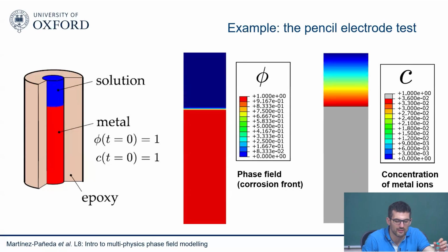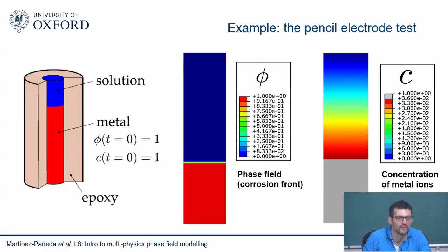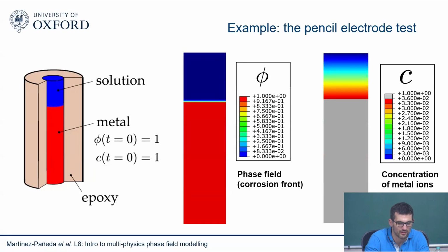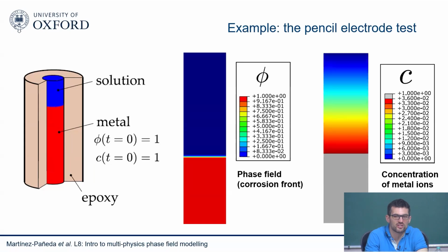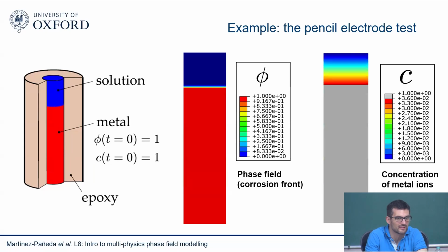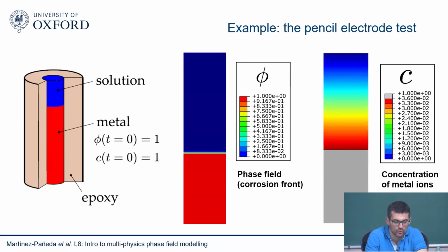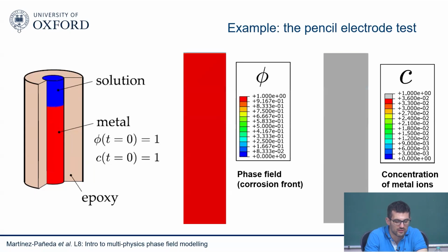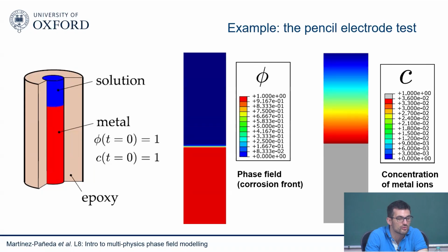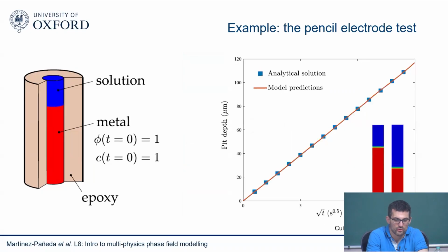Of course, we don't really need phase field to model 1D corrosion, so this is just a benchmark test. But this benchmark test is very useful because, first, there is experimental data that we have seen that we are able to reproduce, but also there is even an analytical solution for the conditions of diffusion control corrosion. So this is the comparison with the analytical solution for diffusion control corrosion, and you can see the model seems to agree very well.